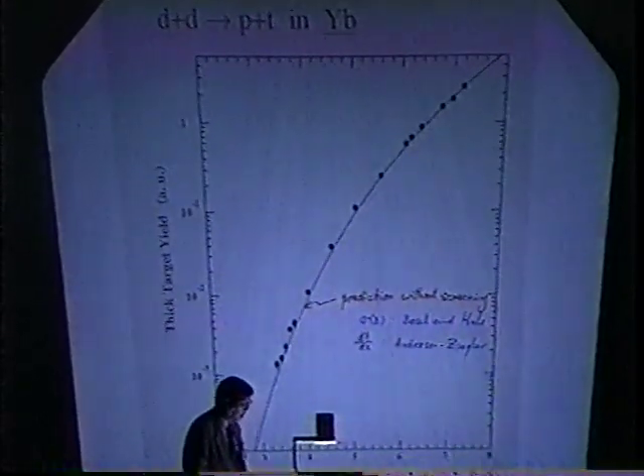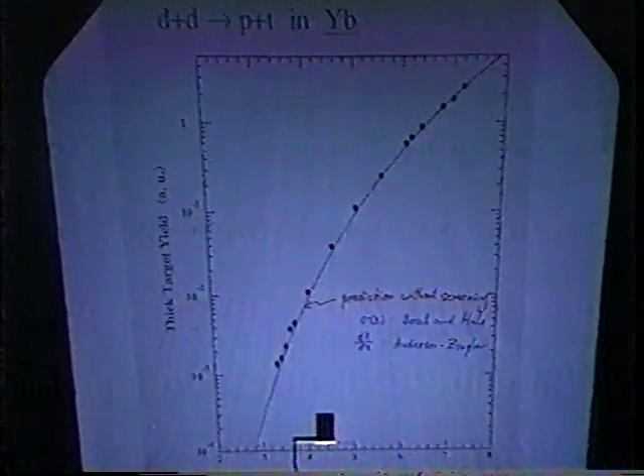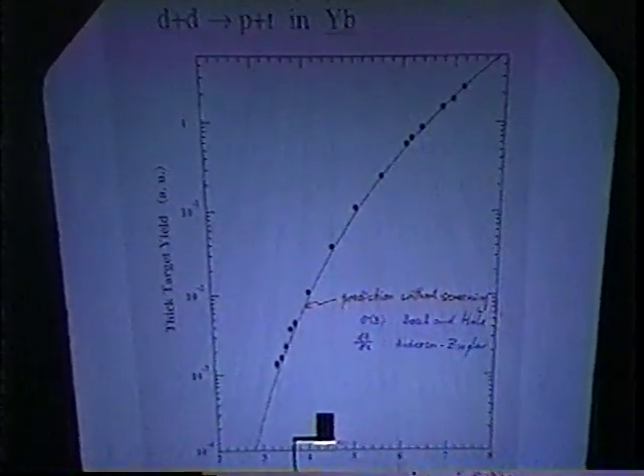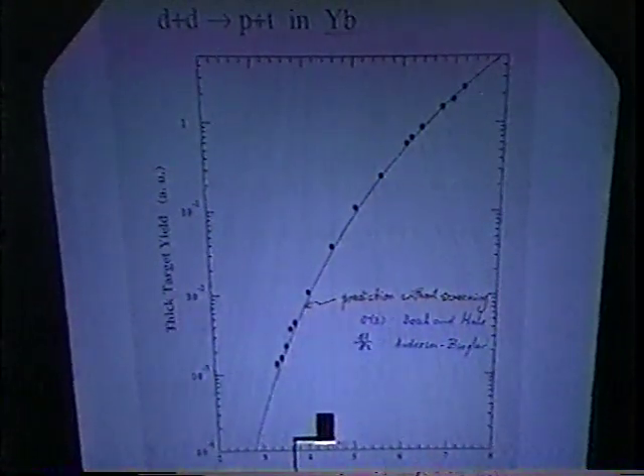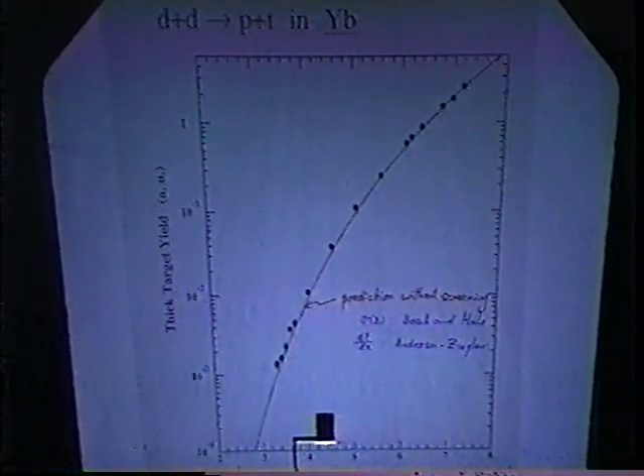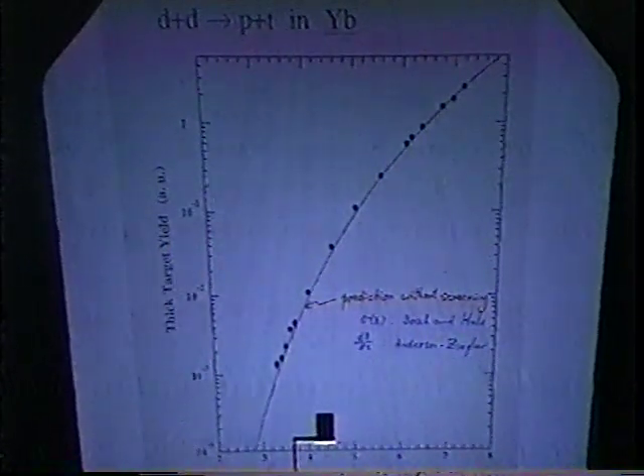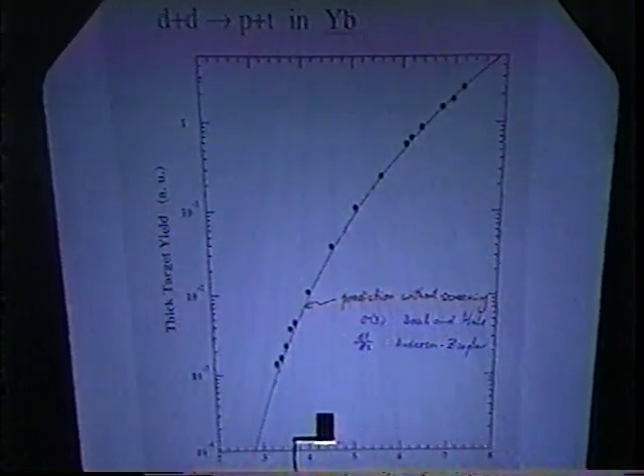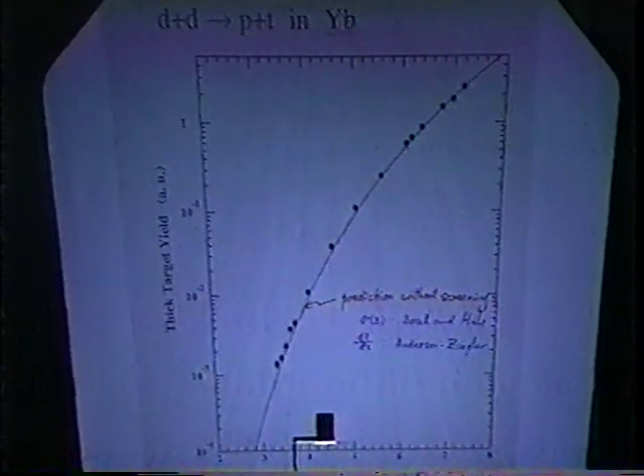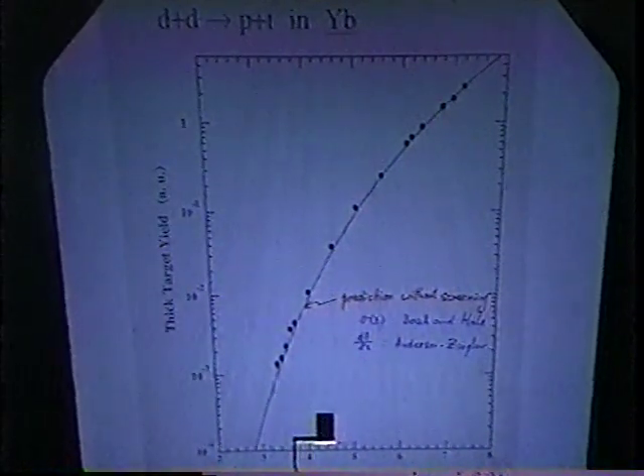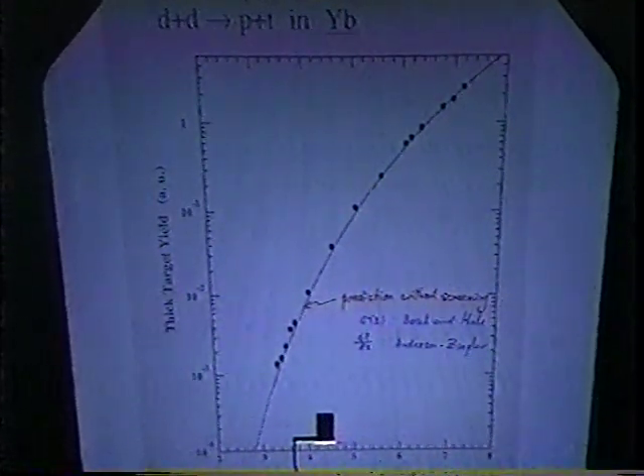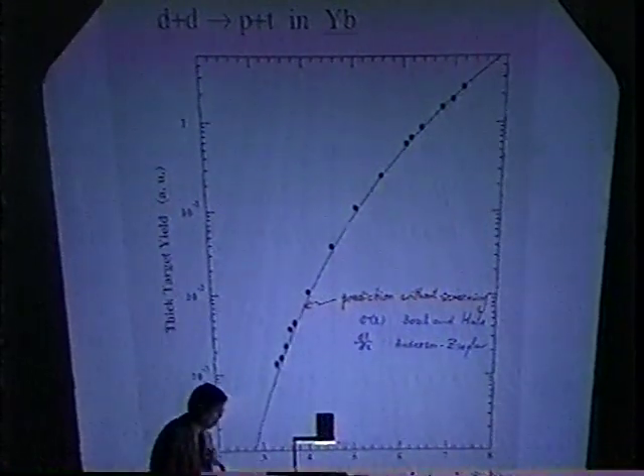We changed the host metal from titanium to the other metals, and we tried one for the ytterbium case here. The same treatment has been done for this measurement and also for the analysis, and this is again the predicted value without screening, and the same data and the same technique was done. And if you look at this carefully, even in this graph, you can see the enhancement at below 5 keV.